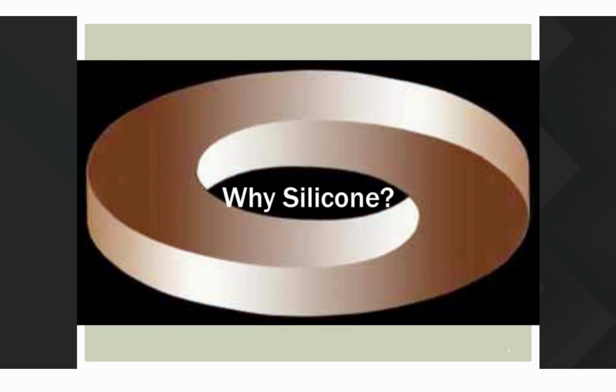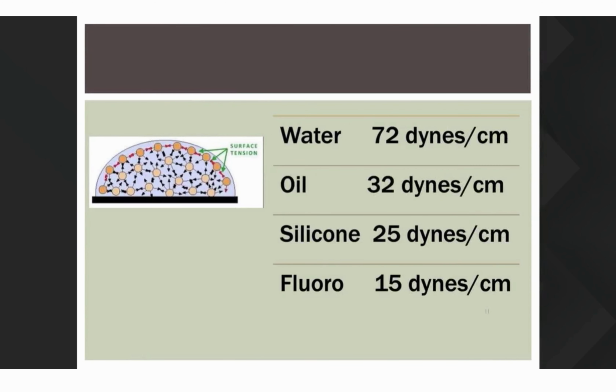So why silicone? Water has a surface tension of 72 dynes per centimeter. When you start doing oil phase, it's 32 dynes per centimeter. So we're generally dealing with surfactants that get to that kind of level. But when we start dealing with silicones, we drop into the 20s. Now remember, I said just a short time ago, small differences in surface tension can really be identified in aesthetics.